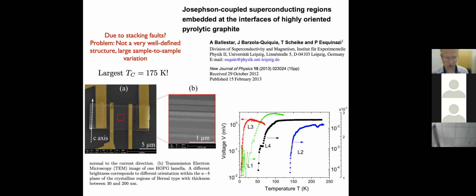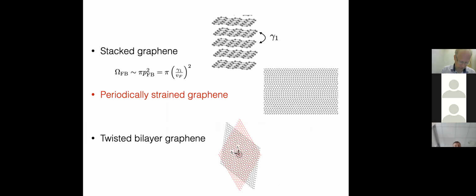This is work from 2013 from Leipzig, where they found a resistance transition in such graphite systems at up to 175 Kelvin, or maybe 150 or so. This is a log scale, so it depends on where exactly you put the transition temperature. The problem was that they did not know the structure of the system so well, so it is not very easy to make a theory on this, and there was also a big variation between different samples. But the bottom line was that stacked graphene can have flat bands whose size scales with this gamma 1 coupling.